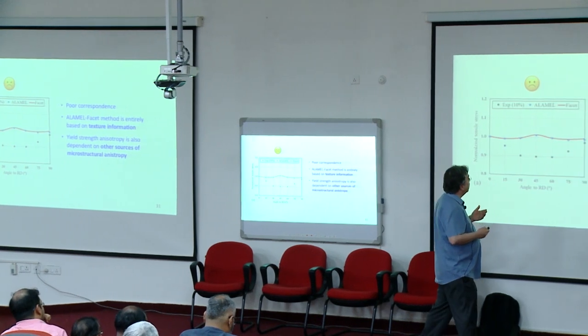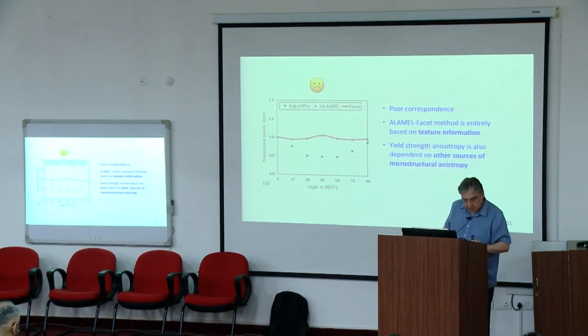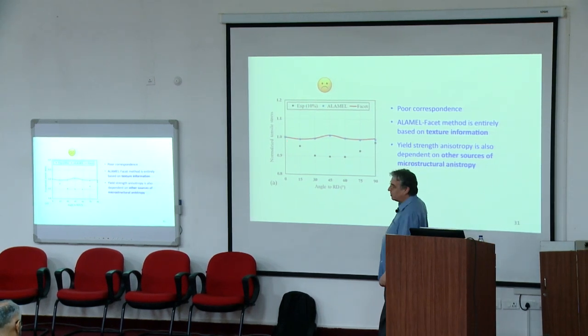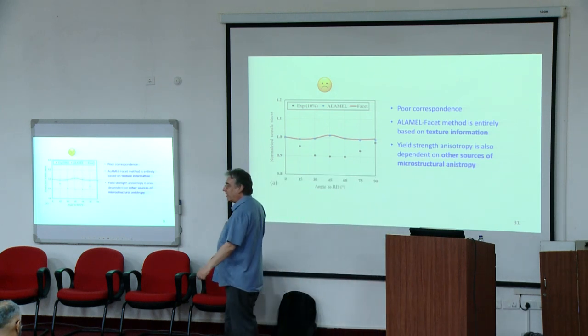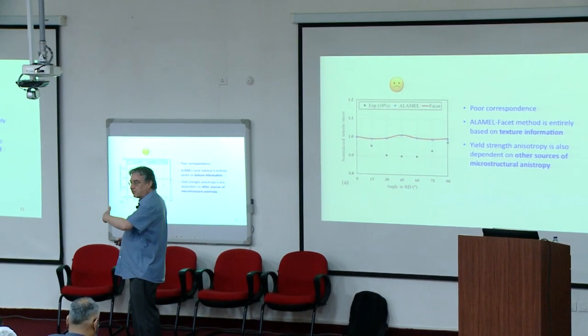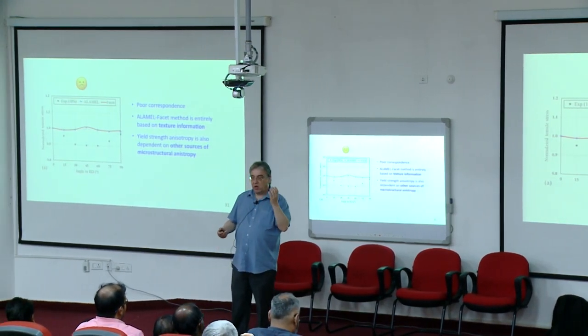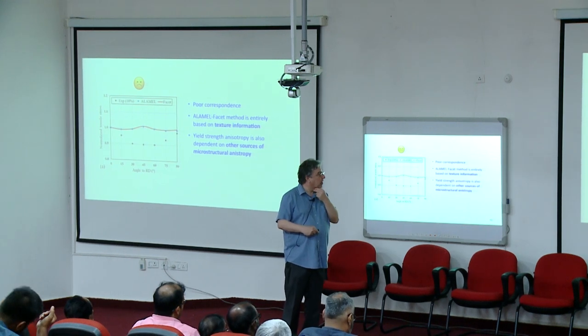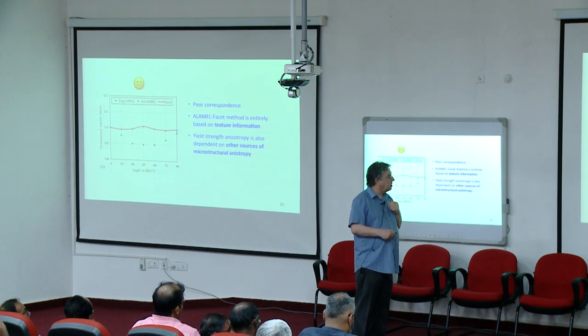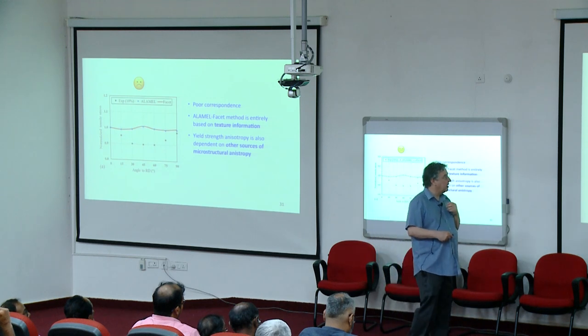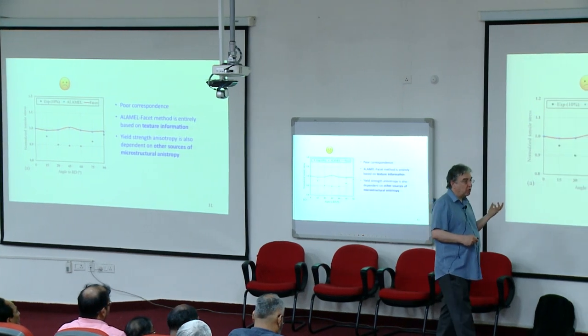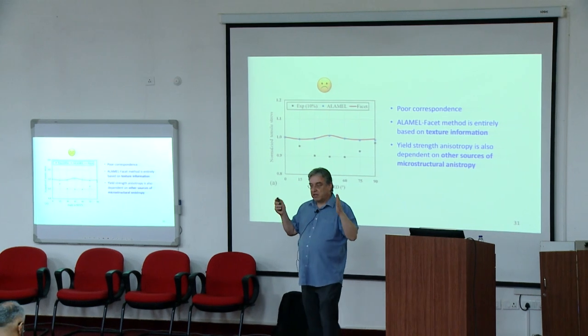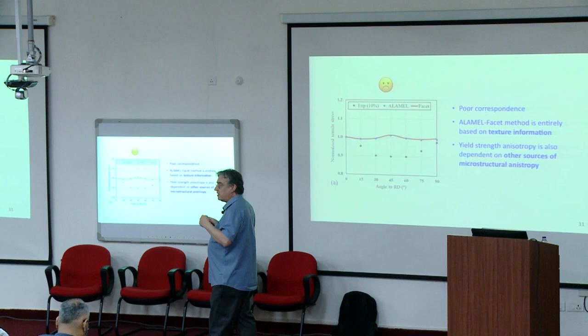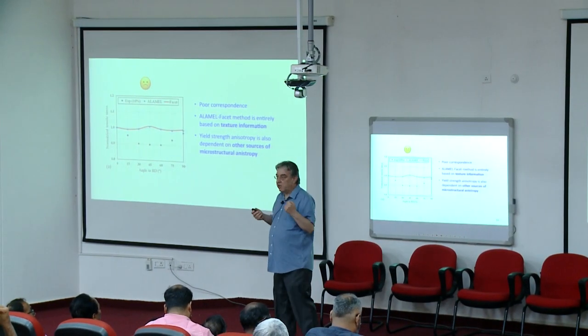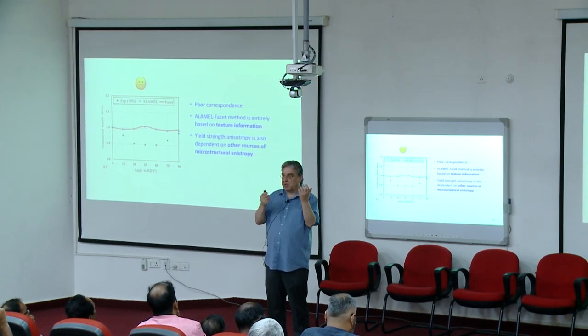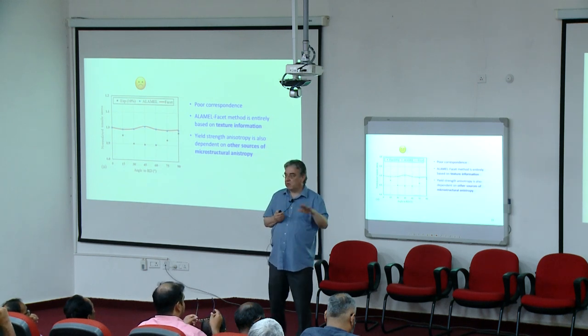Okay, so I think I have convinced you. You may say, you have talked a lot about the things that you can do, but you didn't talk a lot about the problems that you could not solve. Well, there were still about 10 slides about things that we have tried to better model the strength anisotropy, but to be honest, they all failed. We have to continue working on this. At this point, we think that the yield strength anisotropy is dependent on other sources of what I call microstructural anisotropy, which we did not consider. We only considered, in this case, the crystallographic orientation and the grain size. Perhaps it really has to do with how the dislocations are configured with respect to each other in the microstructure, but we didn't model this because that's another issue.